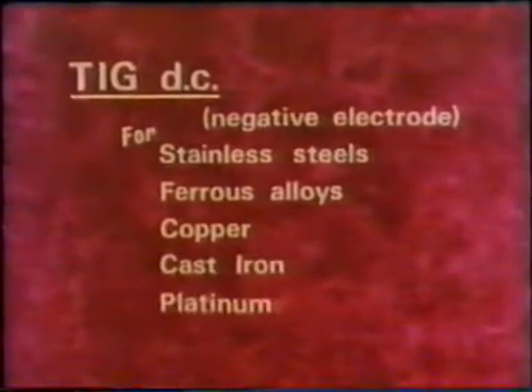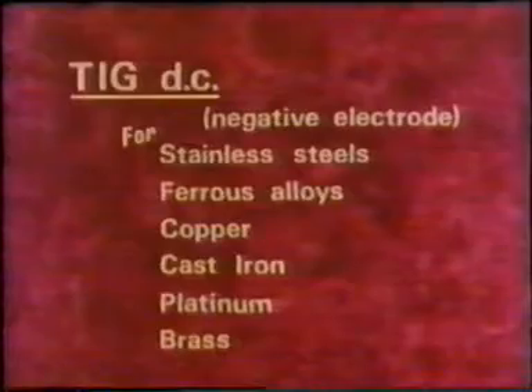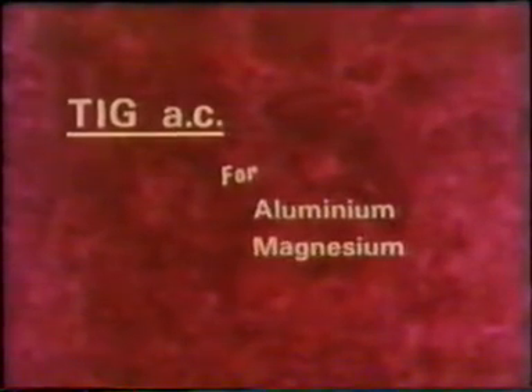Here's AC welding of aluminium in real life and at normal speed. Notice the clear and tranquil weld pool, completely free of that oxide that can be seen retreating in front of the arc. So the rule is TIG DC with a negative electrode for steels, ferrous alloys, copper, cast iron, platinum and brass. TIG AC for aluminium, magnesium and their alloys.